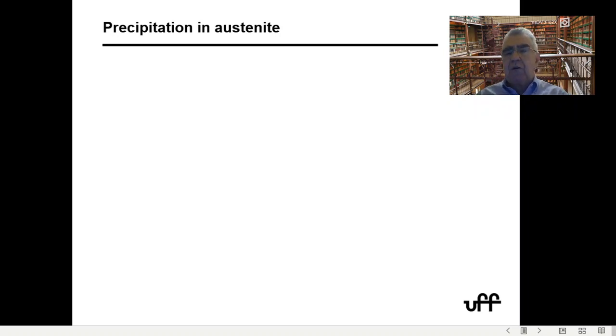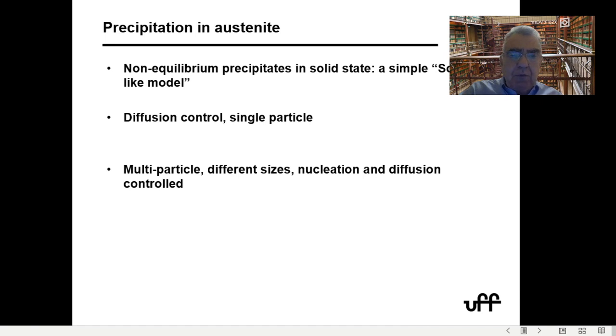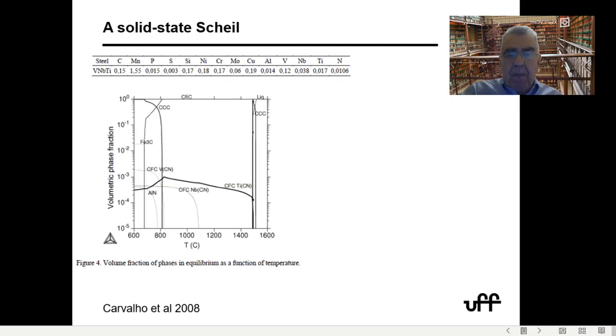Now, the most interesting thing is that people do a lot of work only on the precipitation. Of course, there's a lot of information that is essential for proper processing that is happening before the moment when you're just going to do precipitation. I'm going to show you we can do a simple SCHEIL-like model in austenite that does a very nice prediction. We can do diffusion control in a single particle, which I don't think I'm going to show you today. And then you can do multi-particle, different sizes, and nucleation and diffusion control, which is the latest news in the area.